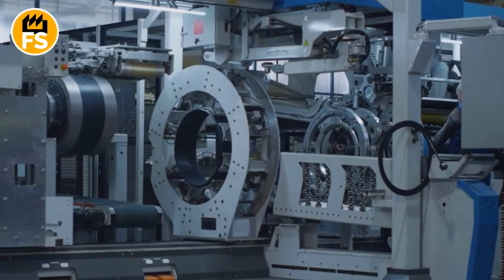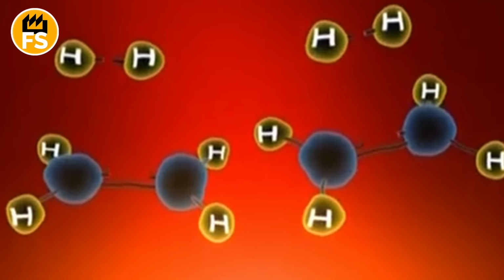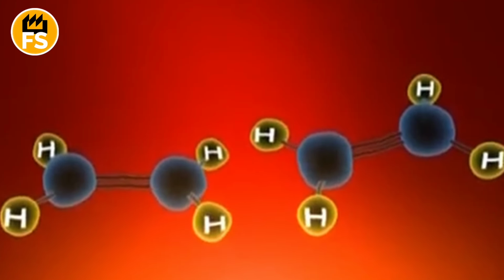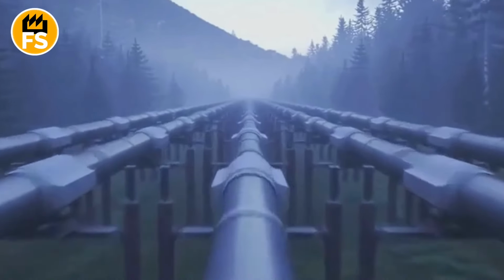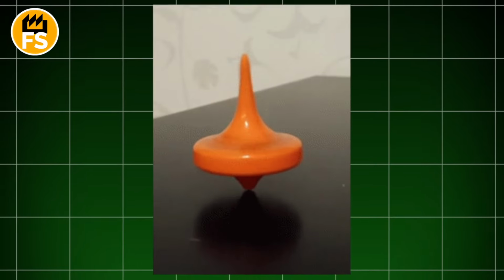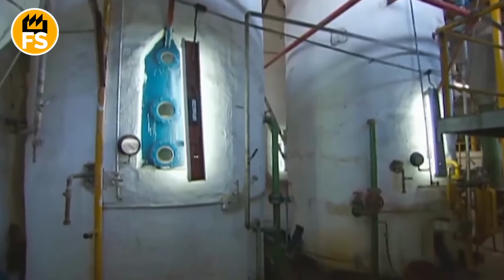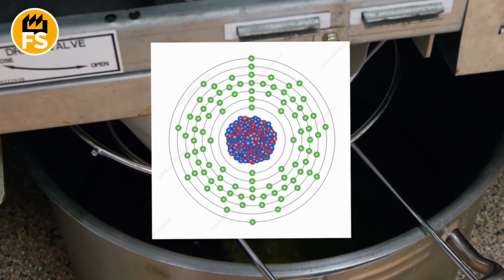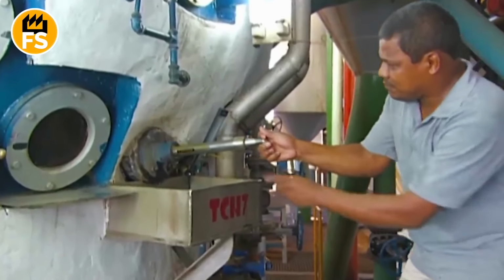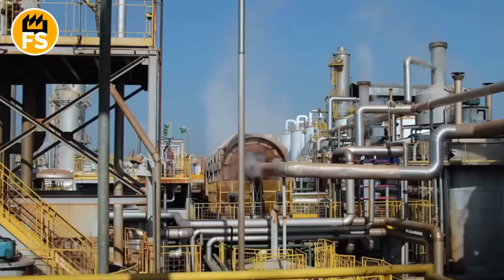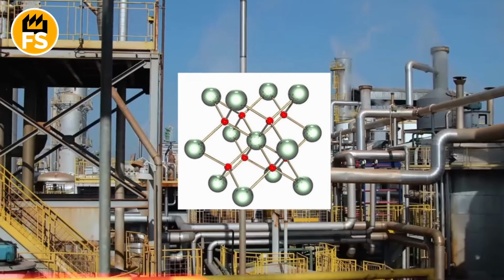Imagine a giant, noisy workshop the size of several football fields, filled with thousands of identical, tall, metal column-like devices. These are gas centrifuges. Each of them is a high-tech top that rotates at supersonic speed, making tens of thousands of revolutions per minute. When our uranium gas is pumped inside, the magic of physics begins. The heavier gas molecules with uranium-238, under the action of centrifugal force, are pressed against the walls of the centrifuge, and the very slightly lighter molecules with uranium-235 remain closer to the center. This is a microscopic difference, but it is enough.